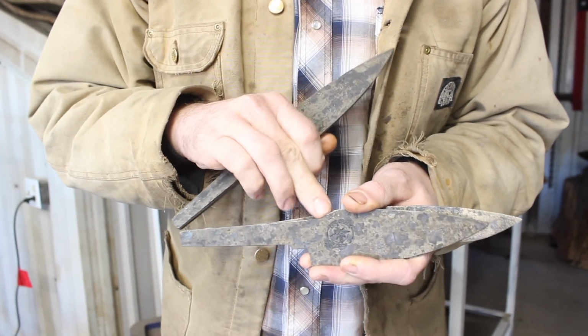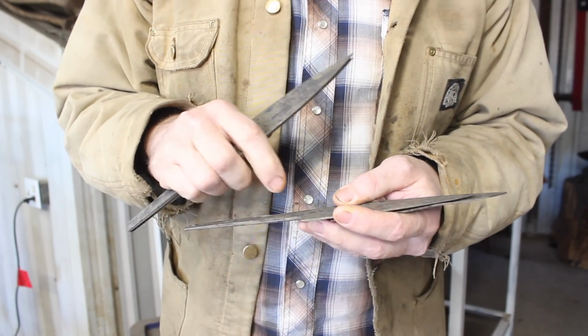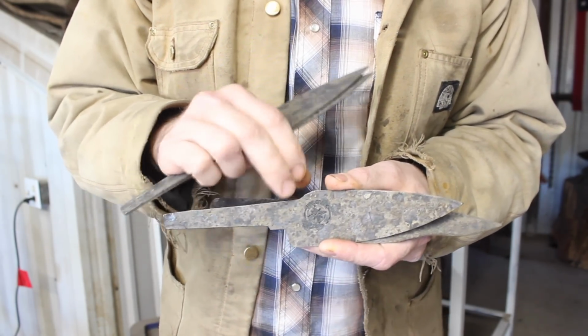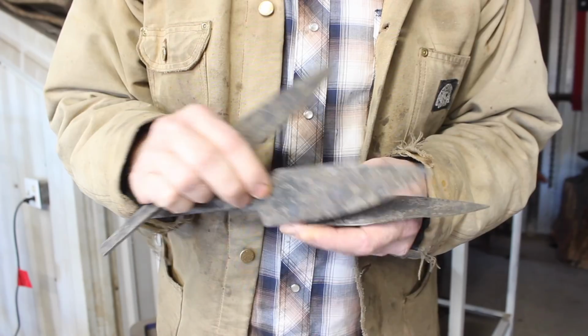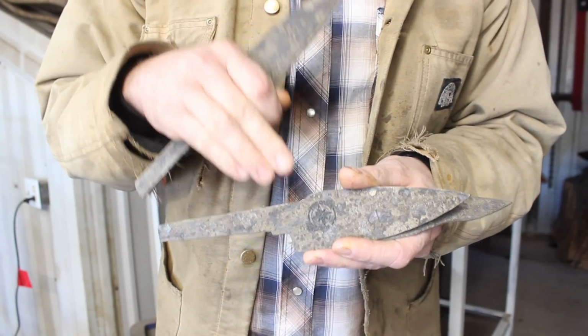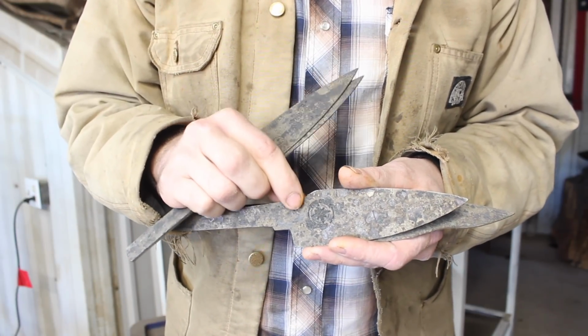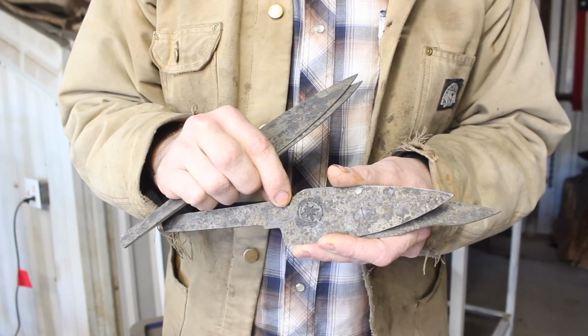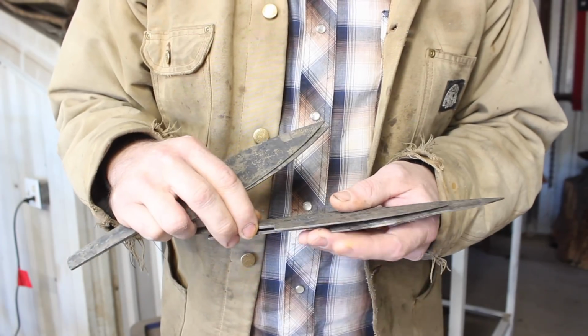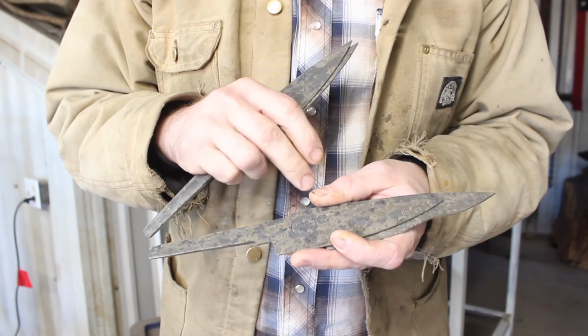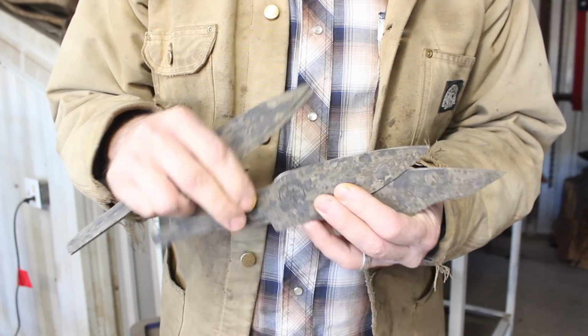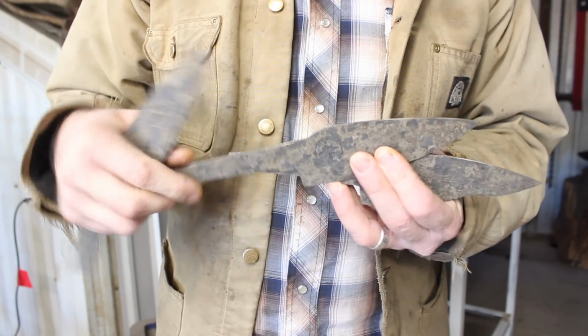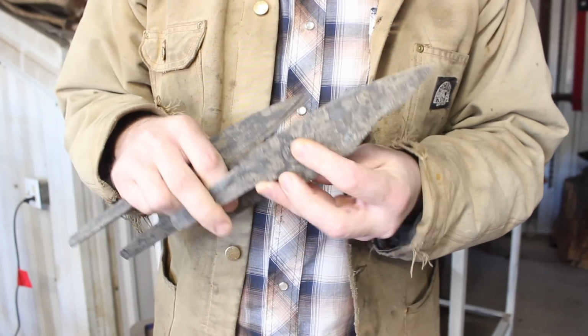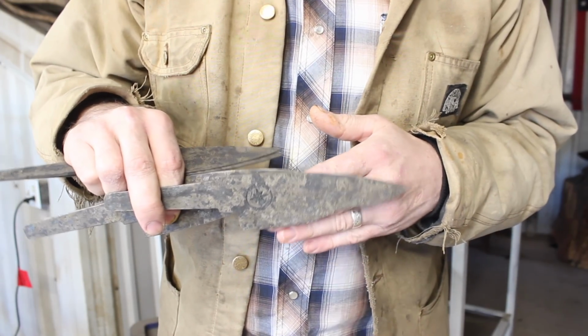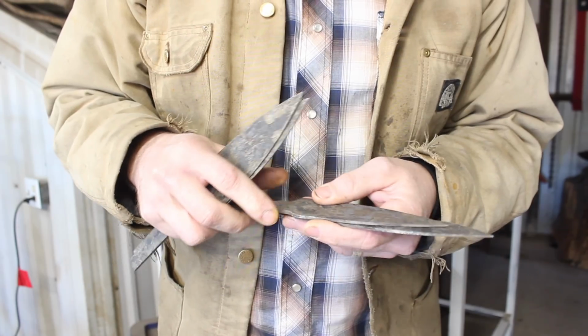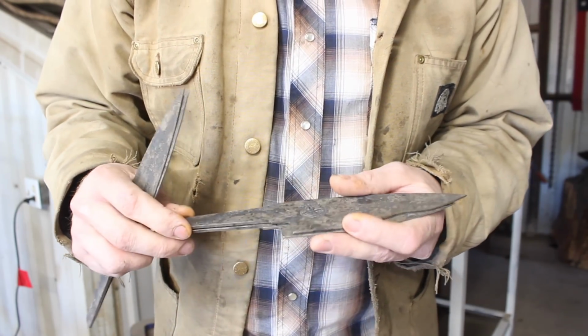So what happened is that a couple of small delaminations where the forge weld didn't weld together, and you basically have what looks like a crack, but it's where the pieces of steel did not forge weld together fully. These blades are perfectly fine. These two had a couple of spots where we had issues, and I had to grind those out. And so you can see on this particular one here and this one here what I ended up with, which was not what I wanted, of course. So let's talk about that. How did that happen and how to avoid it?